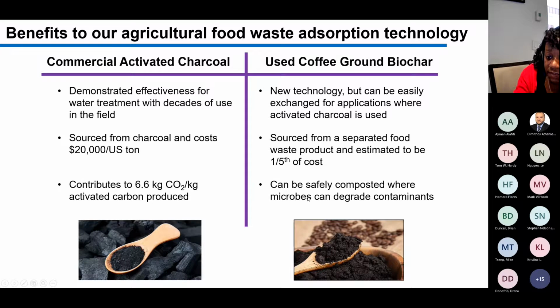And what we're going to investigate in the future is how to dispose of the coffee ground biochar once it's done removing contaminants. So with activated charcoal, what you would do is pyrolyze or re-incinerate the material to hopefully burn off the contaminants that are adsorbed and then recover the adsorbent. Here we could think about other alternatives for disposal that are less energy intensive, like composting, which is what you would do with used coffee grounds anyway. So these are things that we're going to investigate in the future. And again, we have some hope for this material because we did a test comparing our used coffee ground biochar to a commercially available activated carbon that's used in water and wastewater treatment. And under certain conditions, we have equal removal of compounds like PFAS that are, again, really toxic and pervasive in the environment. So these types of comparisons we'll also be making in the future.